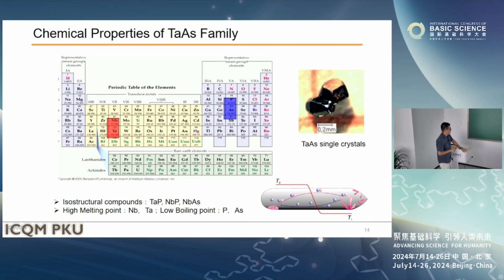So at this point, it is difficult to grow the crystal just from the liquid, right? But another way is you can actually grow the crystal by chemical vapor transport, meaning you're using some vapor of iodine or arsenic vapor to transport the materials from the low temperature or high temperature side to the other side. And at that side, it will crystallize into a small single crystal.